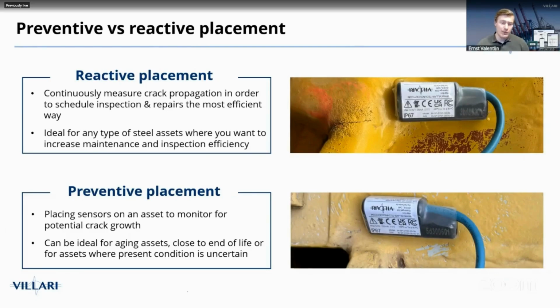In the case of a reactive placement, we see people apply the sensors in locations where there are already cracks existing or defects that have been found. In those cases, like the image shown here, the sensors are placed alongside the path along which an existing crack is expected to continue propagating. This is usually done to give the asset owner some more control and insight over what the actual behavior of that crack is. Is it still growing? How fast is it growing? Is it even a fatigue crack, or might it be a defect from welding procedures that is still in the material, but is not actually growing with usage? But that is done in response to a crack that has been found visually or by NDT, to get some more control of that situation.